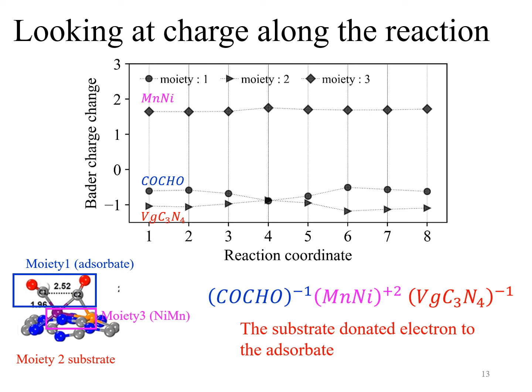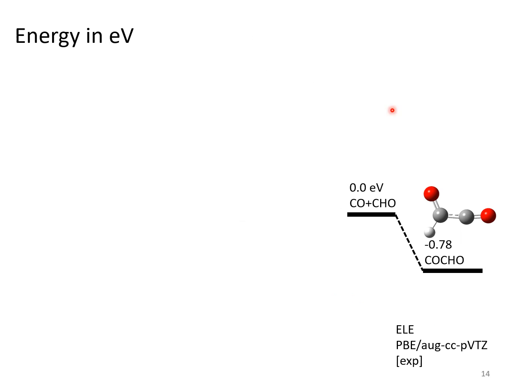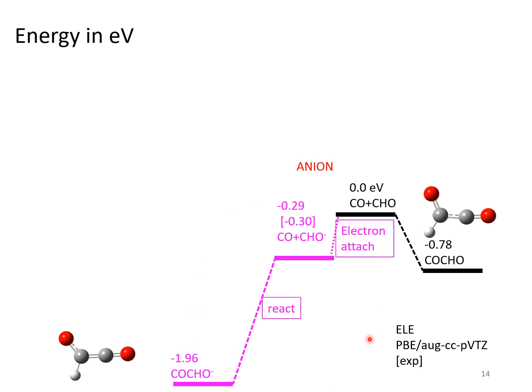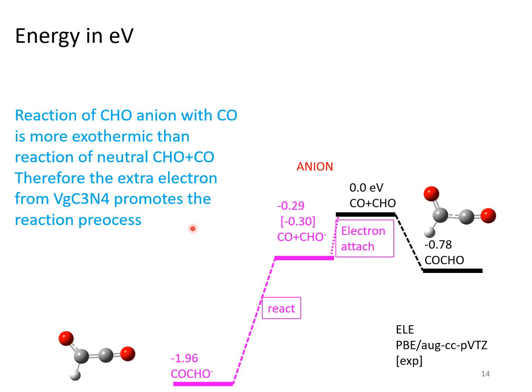Why would donating an electron help? To clarify the effect of the extra electron, we look at the neutral case reaction of CO plus CHO in the gas phase versus if there's an extra electron of CO plus CHO anion. In this case, the heat of reaction is -1.6 eV, much greater than the neutral case. Therefore, in our case, this extra electron from the N-vacancy graphitic carbon nitride promotes the CC coupling reaction.